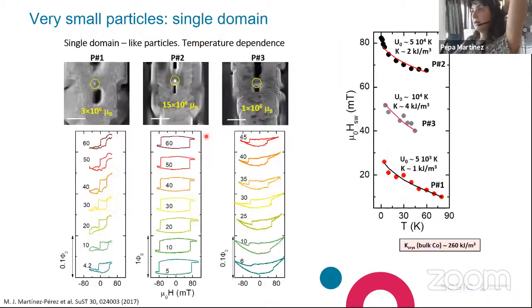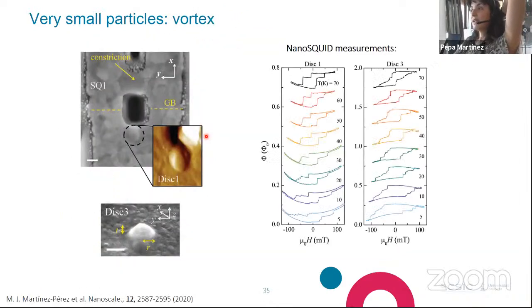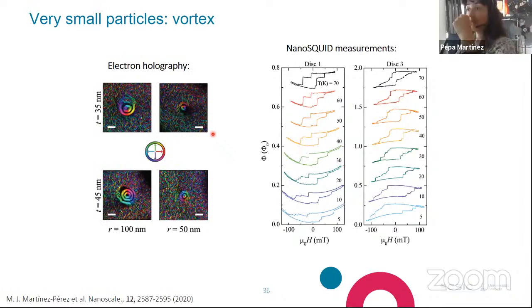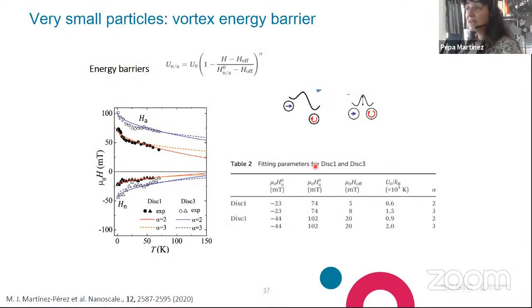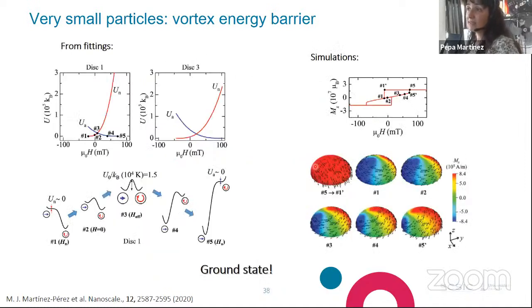But what happens with particles lying here in this purple area? Well, here we found signatures of vortex nucleation, but what we needed to prove is that the vortex is indeed the ground state of the particle. We verified this by electron holography, where the presence of a vortex is really evident, but also our measurements performed at variable temperature allowed us to verify the formation of vortex states, and also that these vortex states are really the ground state of the particle.